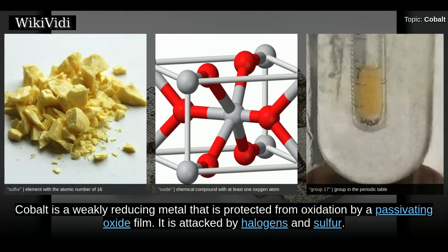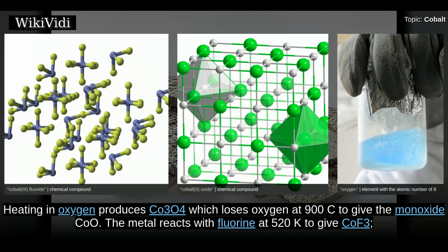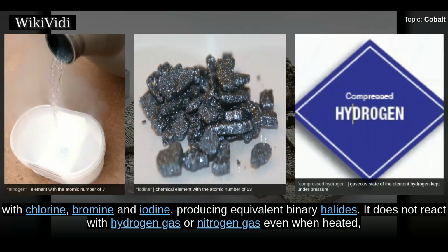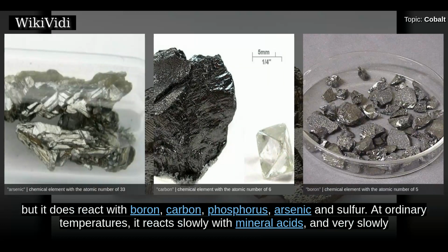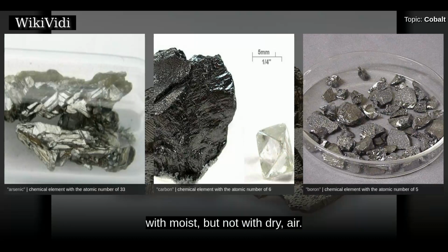Cobalt is a weakly reducing metal that is protected from oxidation by a passivating oxide film. It is attacked by halogens and sulfur. Heating in oxygen produces Co3O4, which loses oxygen at 900 °C to give the monoxide CoO. The metal reacts with fluorine at 520 K to give CoF3, and with chlorine, bromine and iodine, producing equivalent binary halides. It does not react with hydrogen gas or nitrogen gas even when heated. But it does react with boron, carbon, phosphorus, arsenic and sulfur. At ordinary temperatures, it reacts slowly with mineral acids, and very slowly with moist, but not with dry, air.